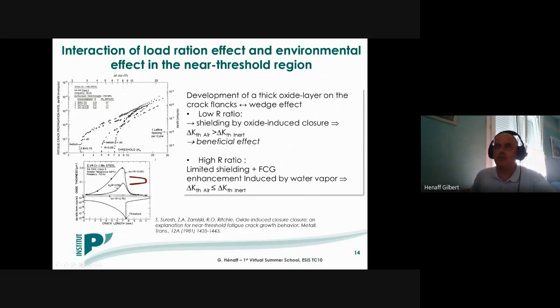Here in helium, you have some traces of water vapor. So that means that for a high load ratio, you have a comparable near threshold behavior. But at low R ratio, where crack closure effects are prevailing, you will obtain a higher threshold in air than in helium containing traces of water vapor. And on this graph, you have some measurements of the oxide thickness on the fracture surfaces in air or in, again, helium containing traces of water vapor.